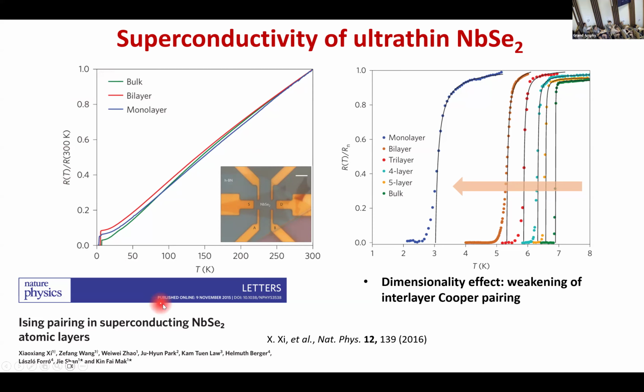So then back then, in Kin Fai Mak and Jie Shan's group, they exfoliate down to a monolayer, and you can see that the transition temperature goes down with the reducing of the thickness. So this dimensionality effect, they argue that when they plot this as a function of the number of layers, then this matches quite well with this formula for the weakening of interlayer Cooper pairing. So you have less layers, so then the interlayer Cooper pairing becomes weaker. So that's why TC becomes lower. This is the idea.